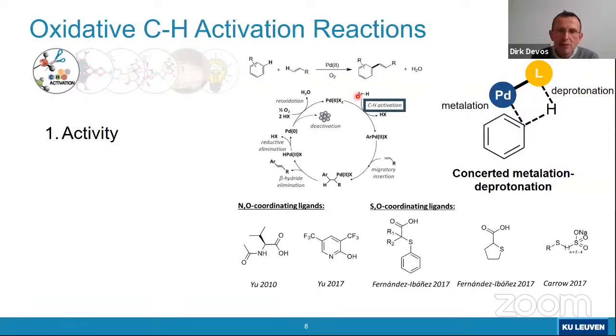That means also, if that is indeed one of the more critical and more difficult steps in the whole sequence, that you could make a lot of progress, that you can make these reactions work much better probably, and that has been a very thriving activity in the field of homogeneous catalysis. If you add a suitable ligand to the palladium, and just a very non-exhaustive list of ligands is shown here. For instance, you will see this ligand, which is one of the very famous ones, the hydroxypyridine type of ligand. But also more recently, Carrow and Fernandez Ibanez in Amsterdam have been using these thioether ligands, often in combination with a carboxylic acid, and they seem to have particularly favorable effects on the CH activation. For instance, if you want to go for an overall alkylation, these ligands support the activity quite well.